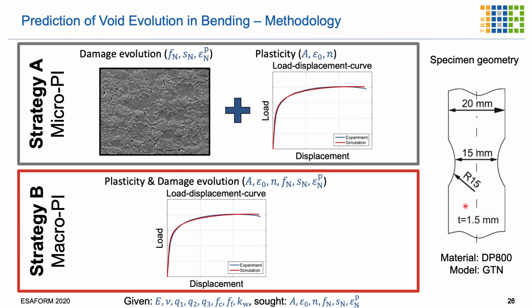So, one important finding in our research center in the first period was that the material property identification is an important issue. We found, for instance, if we use the classical strategy for the damage models to identify the process parameters by the load displacement curve or plus some strain values, you end up with damage values which are not in accordance with our experimentally measured damage values. So we changed our strategy.